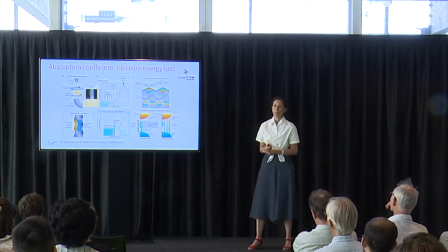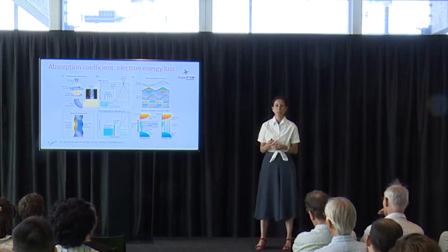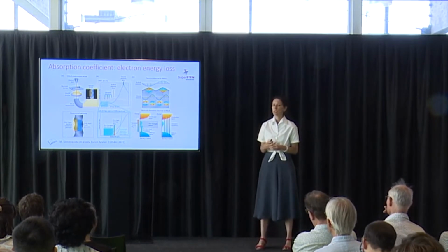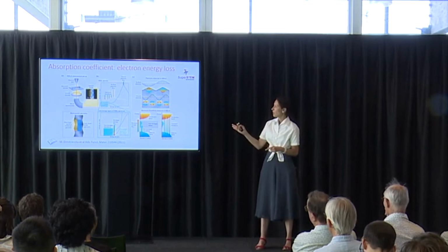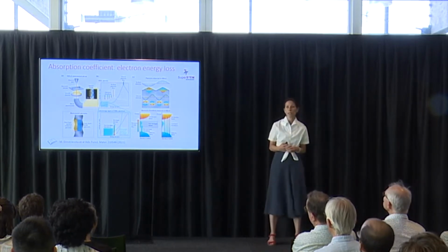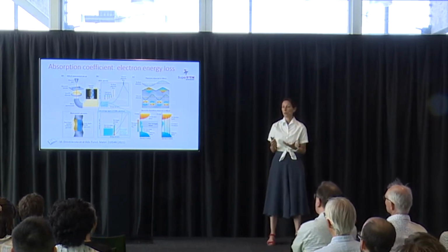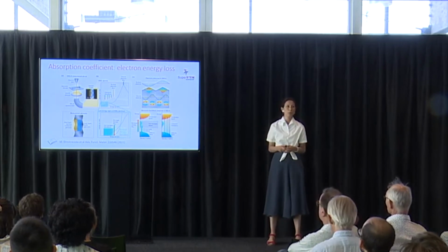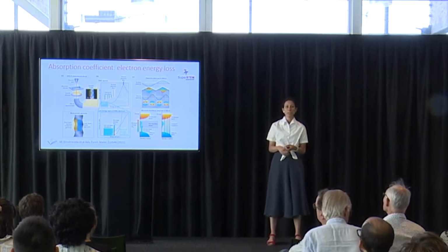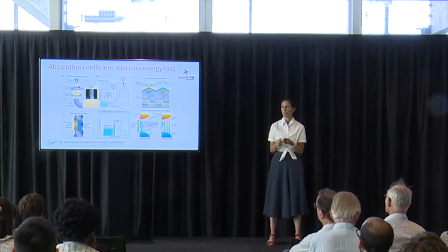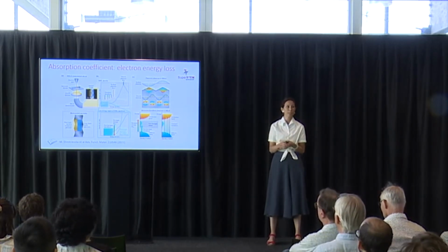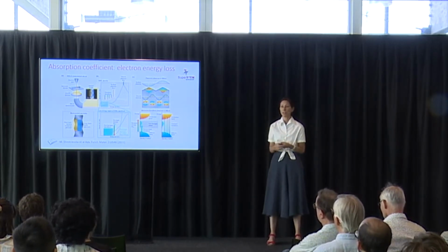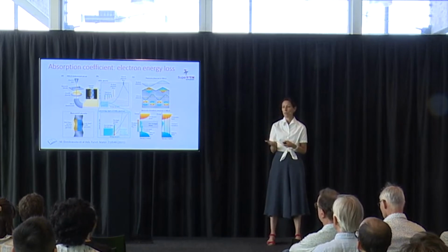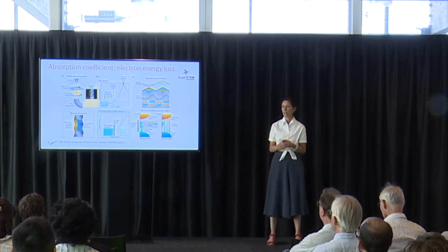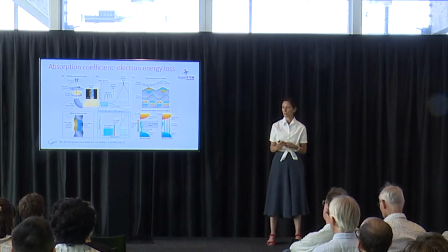We use the nanowires, as I said, to understand the fundamental properties, and this is one of the advantages. So in this experiment here, we went to the SuperSTEM in the UK to look at the absorption coefficient in a different way than we usually do. You illuminate the wires with an electron beam that is highly monochromatic, and you look at the loss of energy of these electrons. And if you have a high-resolution spectrometer, as they have, this doesn't exist everywhere, you can relate this to the absorption coefficient.